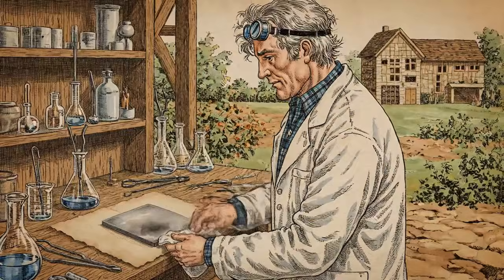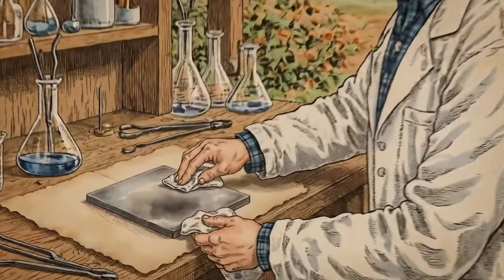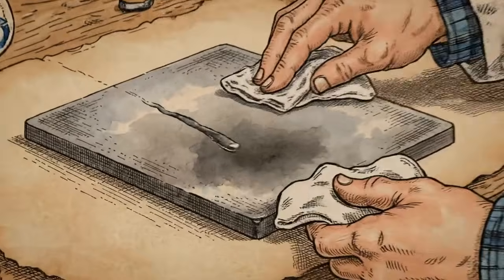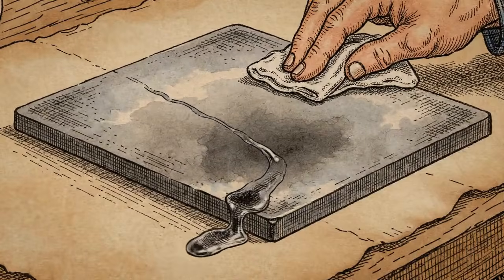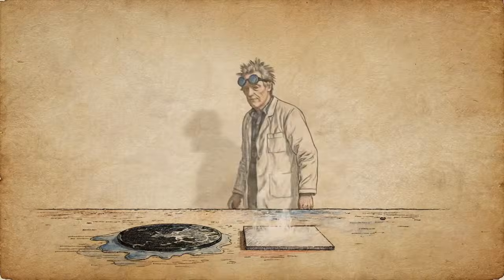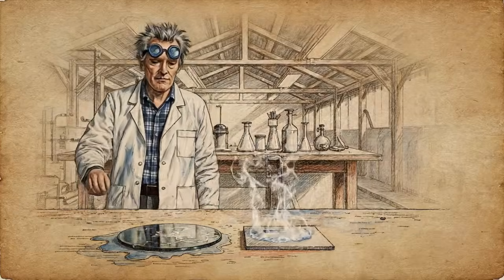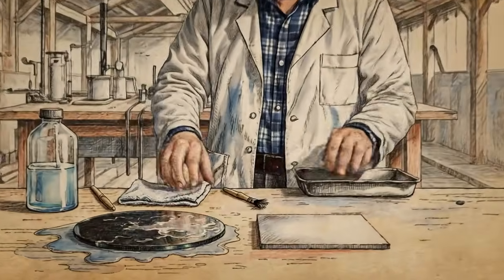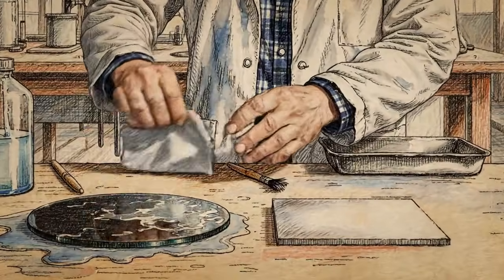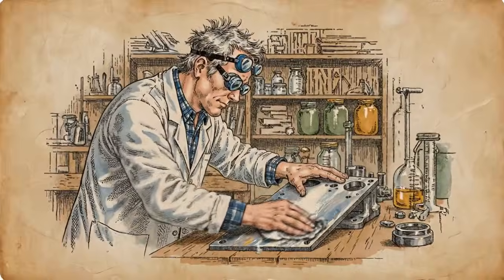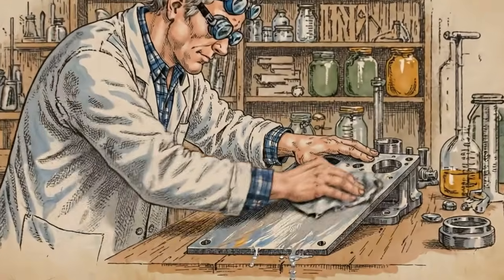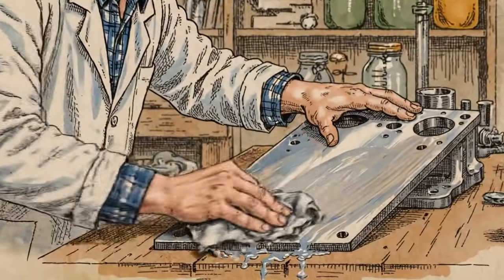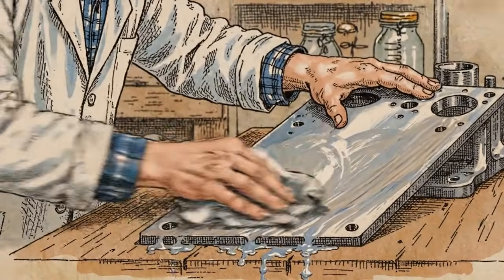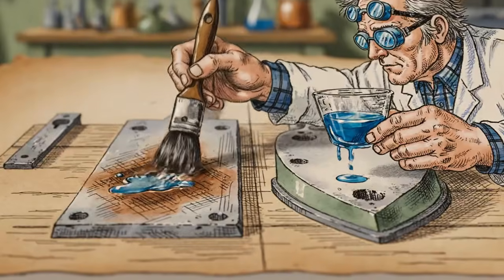The full phosphate conversion, the depth of penetration into the iron grain structure that creates real corrosion resistance, takes a minimum of 20 minutes at room temperature and closer to 30 if the metal is cold or the solution is dilute. The color change at the surface is the signal that the reaction has started. It is not the signal that the reaction is finished. The chemistry is still working in a layer you cannot see. That invisible work is the product. You have to let it finish. So here is the sequence, exactly as you will do it.